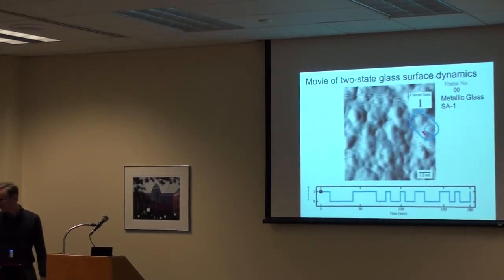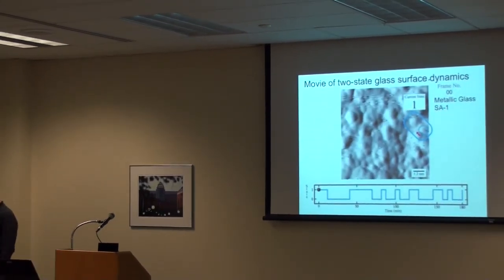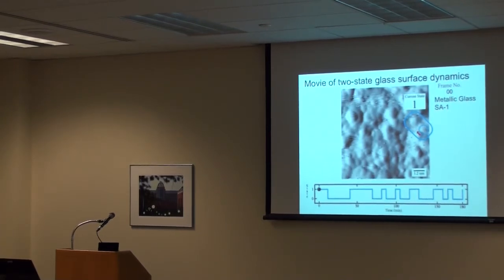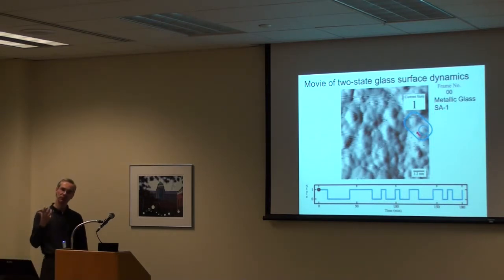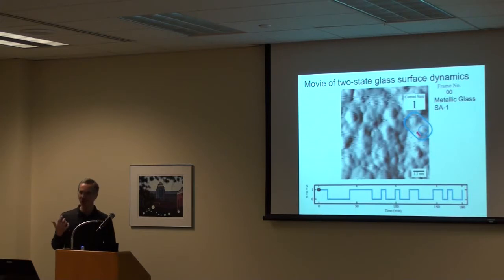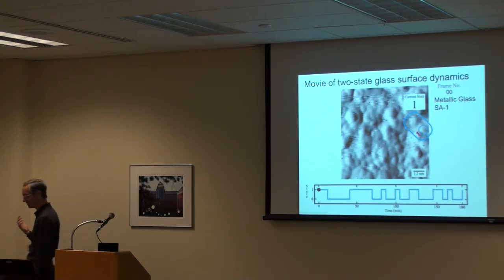Okay? So maybe those are actually those little balls that the glass people are talking about that behave like two-state systems. And so then the thing that Sumit really got going well, which took quite a while, was to be able to scan STM images of the same region of the glass over and over again, hour after hour after hour. People who do STM know how tough that is, to get an image that's good and consistent quality without the tip crashing or something bad happening, right? Because if you want to take an actual movie of dynamics, you don't want just to do a single STM scan, you have to do hundreds of STM scans of the same place, and they all have to look good, otherwise you can't use the darn thing, okay? So he got that to work after a lot of sweat and time being spent.